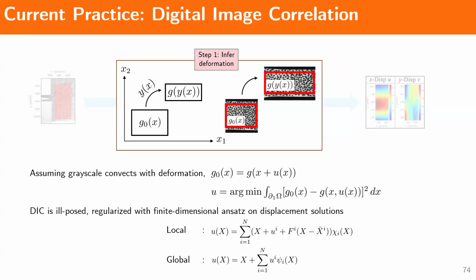The local DIC here, you can see that the deformation field is not going to be compatible. It's not globally compatible. So people take care of this by looking into the global DIC, which gives you compatible fields. But in both of these approaches, you have these, and here is also the regularization parameter. There is no notion of convergence as you keep increasing your subset size, which is n here, or as you keep increasing the number of basis functions that you're using. So there's no notion of convergence and there's no notion of error in these methods.